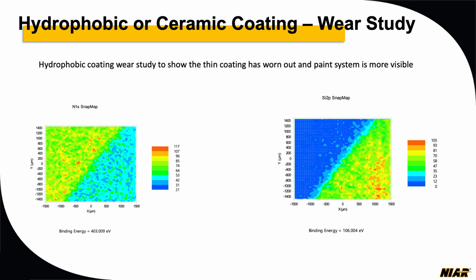Because if they put this material and it just goes on the first flight itself, they cannot put a de-icing fluid on the aircraft. So we did basically a Taber test, and we did a lot of testing in the past. The problem is that hydrophobic coatings and ceramic coatings are very thin. That's why when we got the XPS, that was very revealing data of, okay, if we do a test, how much of the coating is still left. We can do a contact angle and basically find out the surface free energy and the contact angle and see the ratios on that. But the coating itself, how long does it last?